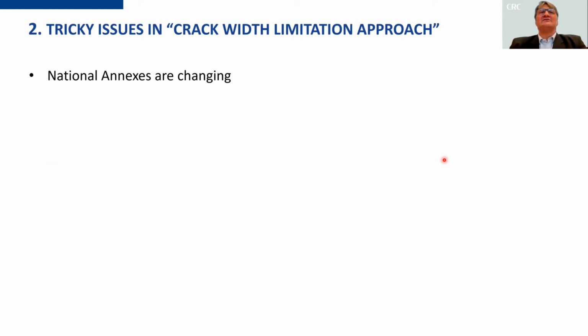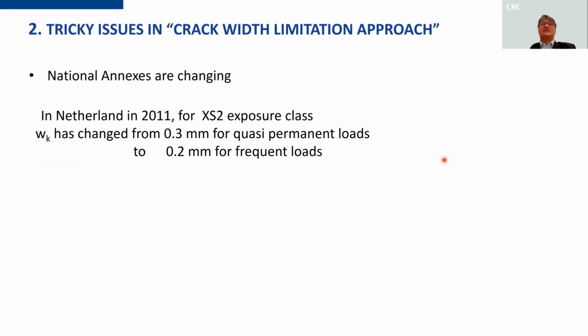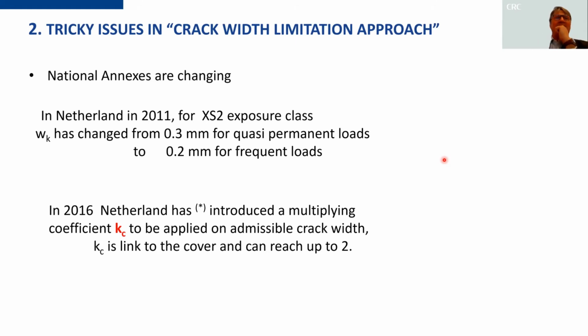Another tricky issue is that national annexes are changing. For example, in the Netherlands in 2011, for XS2 exposure, the admissible opening changed from 0.3 millimeter for quasi-permanent load to 0.2 for frequent load. That means more than 50% more reinforcement. Why? Five years later, the Netherlands introduced a multiplying factor, coefficient KC, to be applied on the admissible crack width.